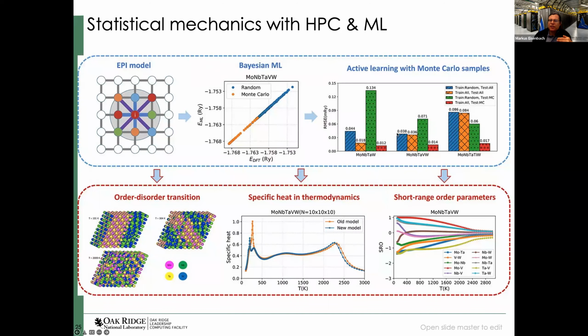yeah. So you see that we then go from the original error in the training set to a much smaller one that then allows us to identify order-disorder transition in these materials, where we go from some high temperature disordered phase to the emergence of partial order to a fully phase separation into two binary systems in this.